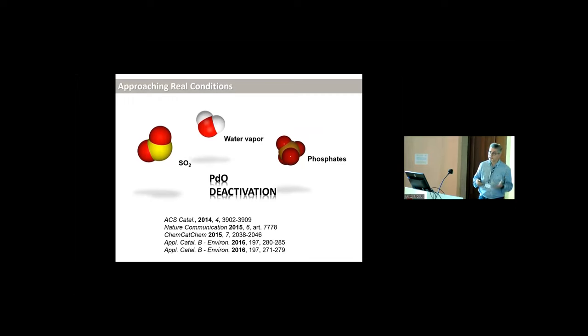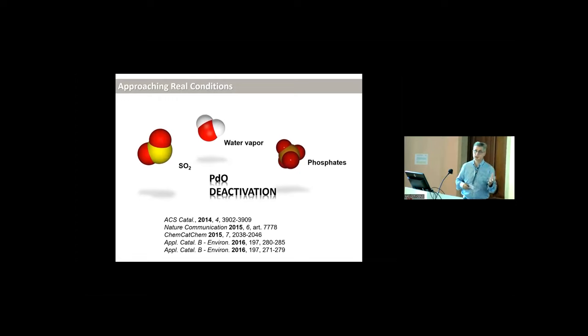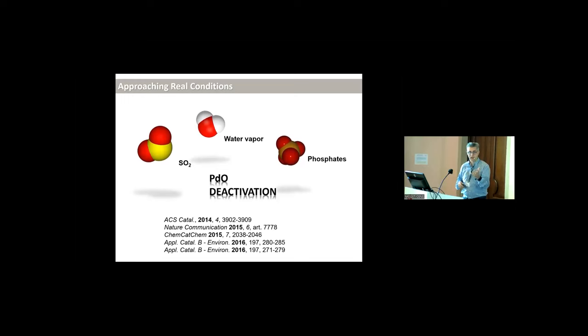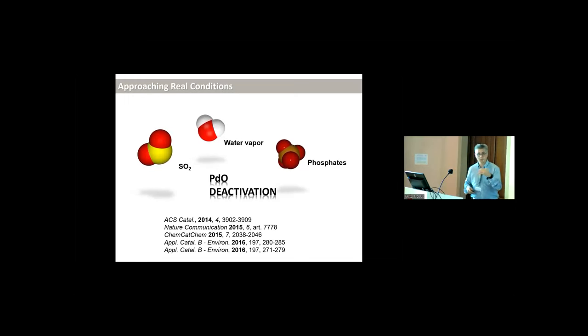However, in reality, industrial processes are nasty. You have molecules like SO2, water, phosphate from lubricant that create huge problems to this catalyst. So you have really a deactivation in real, industrial conditions. So we spent a lot of time trying to modify both the core and the shell. The core by making a bimetallic system, platinum-palladium alloys, still with a sophisticated synthetic approach. And the shell was replaced, because cerium was deactivated partially by water and also phosphates, making cerium phosphates, with stable compounds with cerium, zirconia, etc., etc.